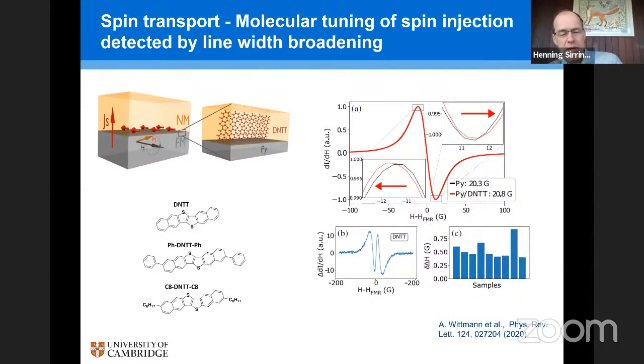If you compare the line widths of the ferromagnetic resonance before and after the deposition of the organic material, you can see a small broadening of the line width once you deposit the organic molecule, which indicates that there is some spin injection from the ferromagnet into the organic semiconductor. And we were able to analyze the magnitude of this spin injection, or the broadening of the ferromagnetic resonance, as a function of the interface structure.